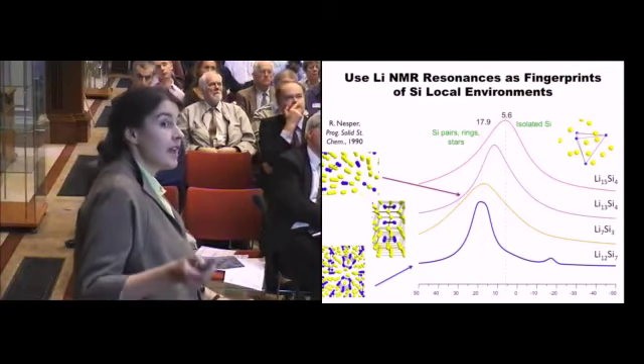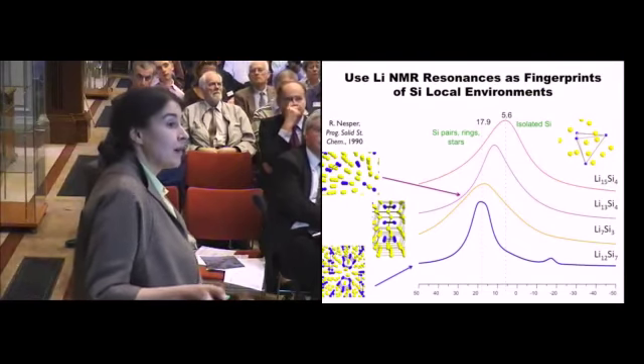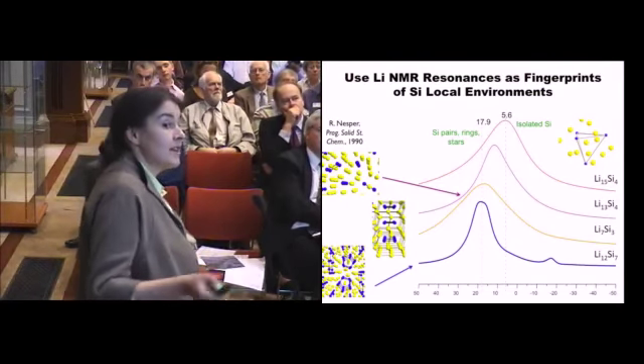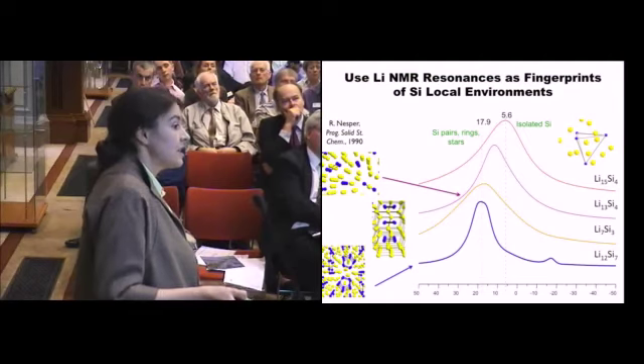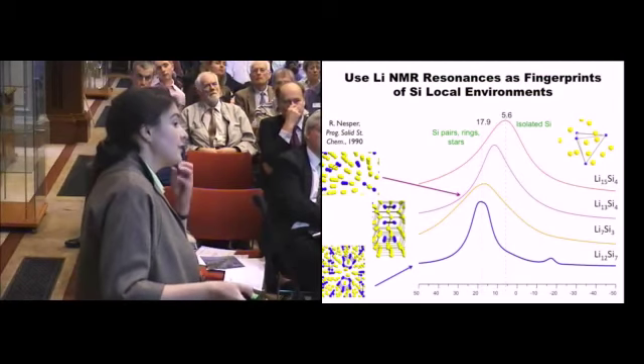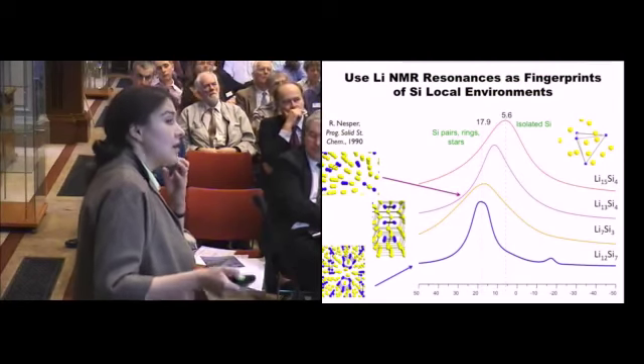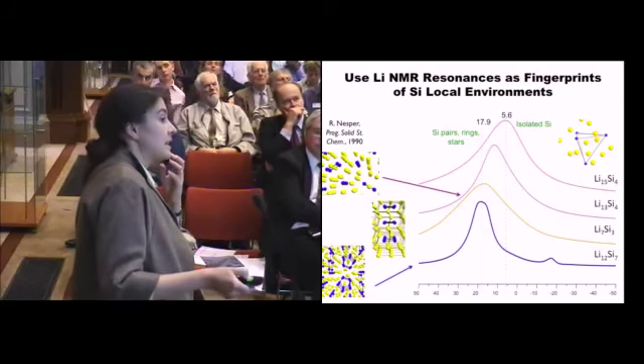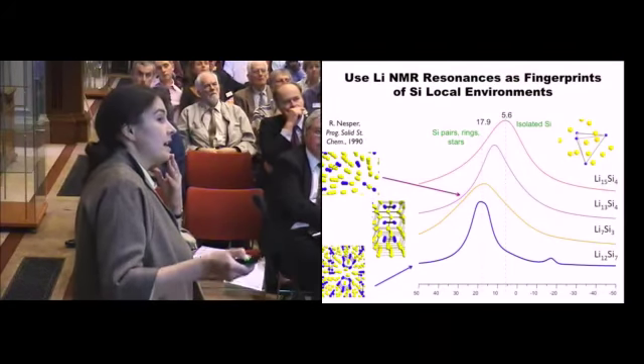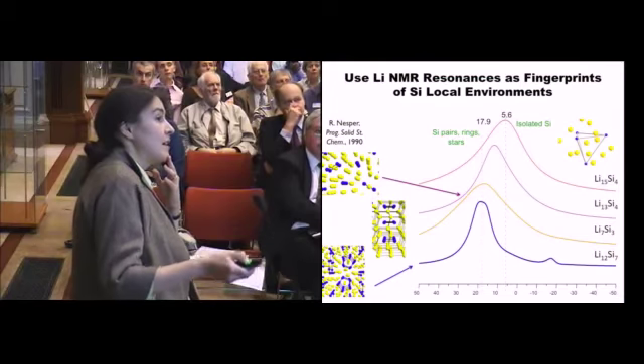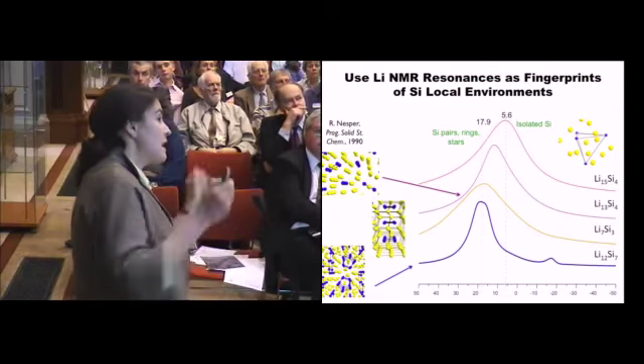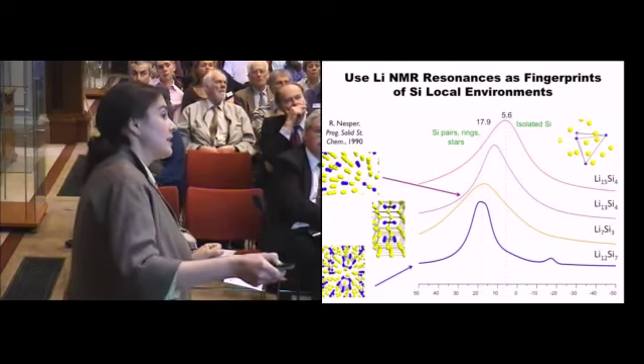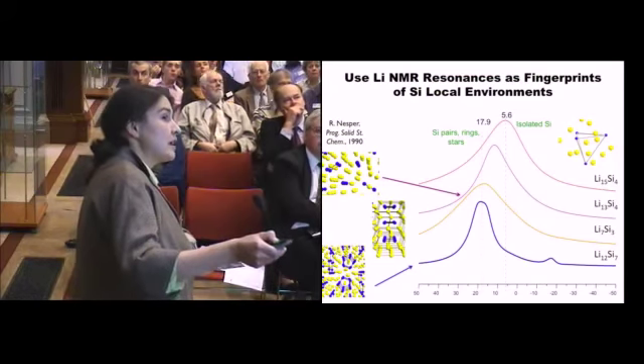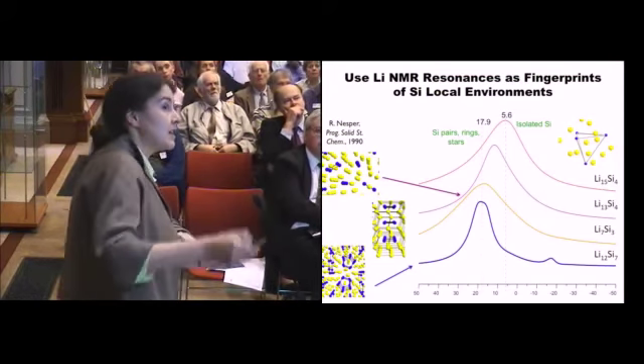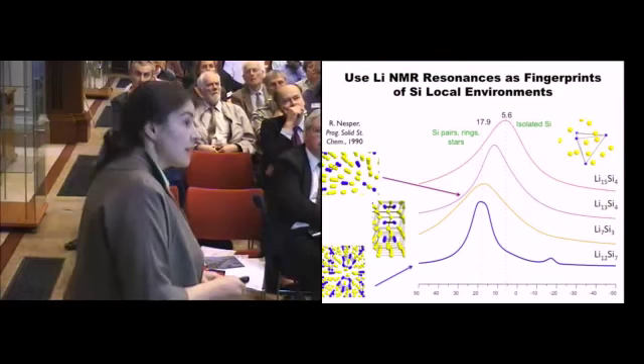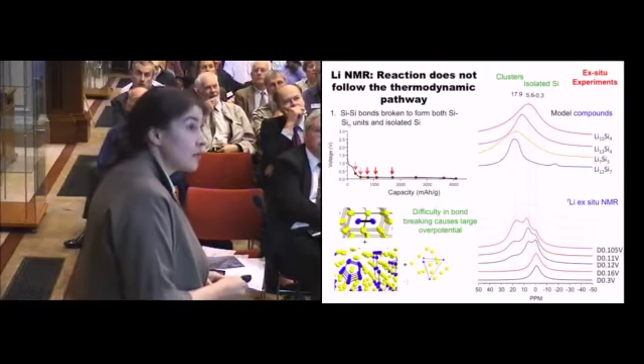So here are the NMR spectra of the different compounds. I have a peak at about 20 ppm for this lithium silicide that contains silicon clusters. So that's a 5-membered ring. That's a star. This compound contains silicon-silicon dumbbells here, and again, it's got a peak at about 18 ppm. I then get to a compound where I break apart the silicons, and I've got isolated silicon anions. I have a peak at about 10 ppm. And when the anions are fully isolated, it's 6 ppm. So I can relate shift to local environment.